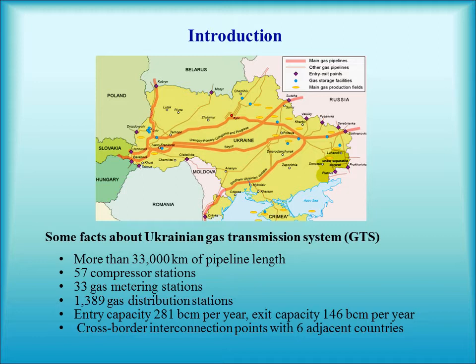And nowadays, around 50% of natural gas from Russia is transited by Ukrainian GTS. However, the age of about a half of gas mains in Ukraine has exceeded 30 years. It is known that long-term operation of gas pipelines causes their in-service degradation. Degradation of structural steels consists in a worsening of their properties in the course of long-term operation that leads to reducing the serviceability of industrial installations, including pipelines. The main danger of the operational degradation is a high risk of brittle fracture, which is rapid and often unpredictable. So in this work, we will discuss the occurrence of brittle fracture in long-term operated gas pipeline steels.